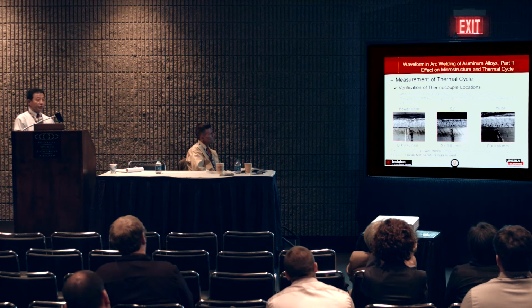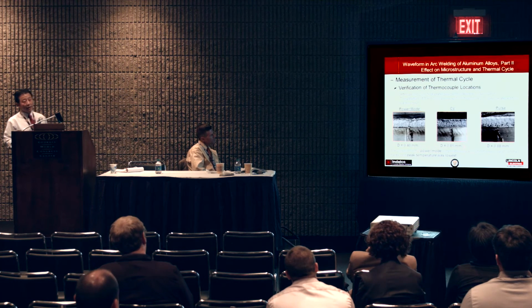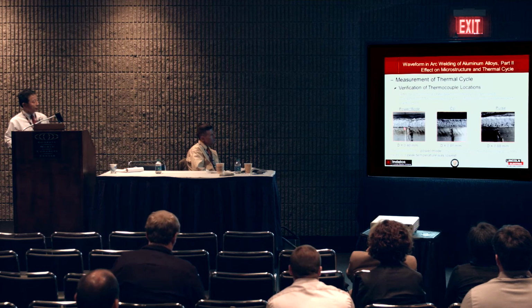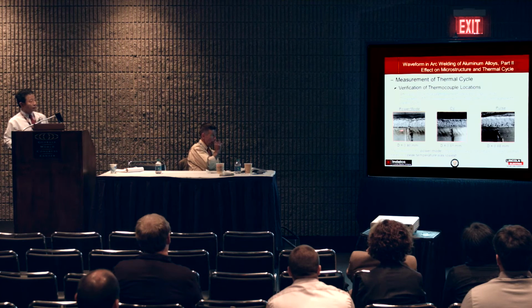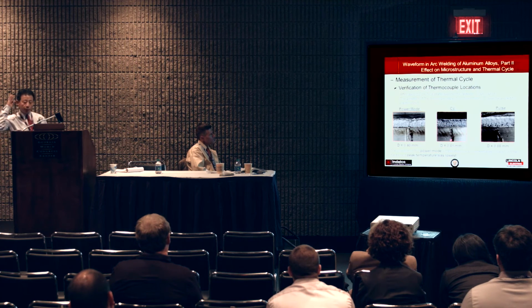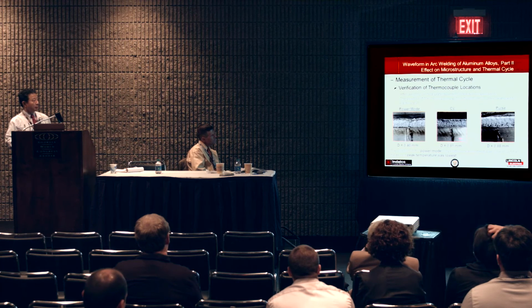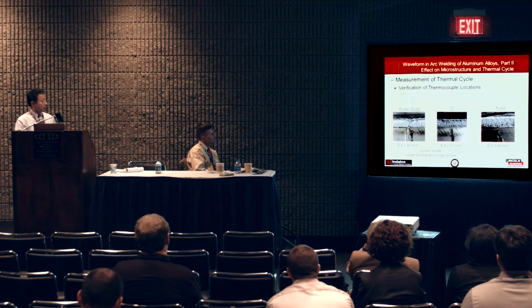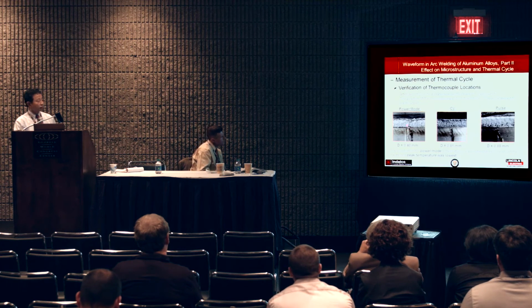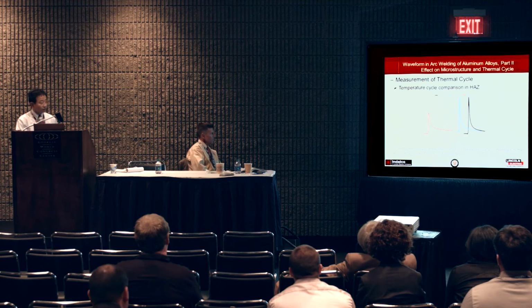So this is after welding, I break the T-joint just to verify my thermocouple location. And it's very, very interesting that even though, for some reason, I put my thermocouple really close, only 0.4 millimeter to my fusion line, there are two reasons. Basically, the origin is the same. Why is it 0.4? Because I got better side penetration for my power mode. That's why it gave me a little bit closer than those ones. Basically, they're at the same spot location, but I measure from my fusion boundary to my thermocouple. You look at that, my thermocouple is fairly close to my fusion boundary. However, I got the lowest temperature distribution.